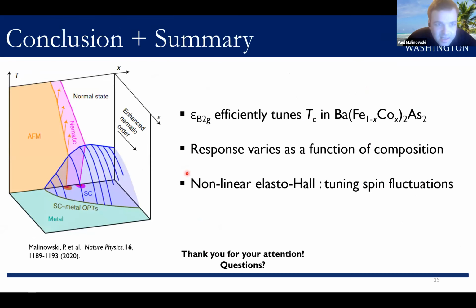Okay, so that brings me near the end of my time. So let me just summarize and conclude. So I've shown measurements demonstrating the effects of uniaxial stress inducing anisotropic strain on the superconducting state in the cobalt-doped barium iron arsenide system. And the effect turns out to be quite drastic, with strain proving to be an efficient tool for tuning TC. Furthermore, the way that this response varies as a function of composition provides insight into how the competing phases of nematicity and magnetism and their fluctuations relate to superconductivity.